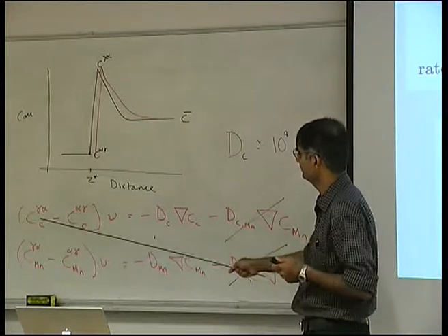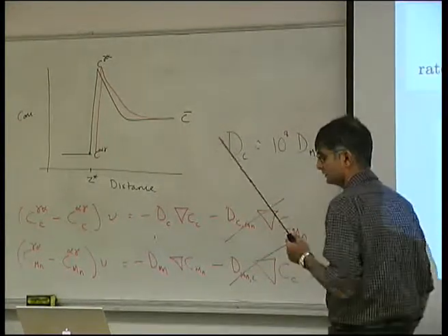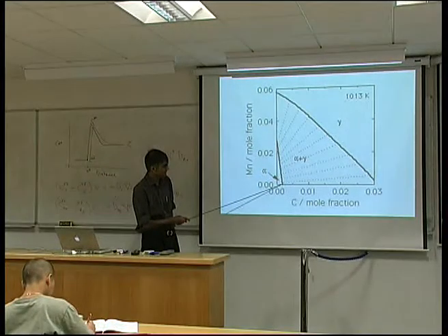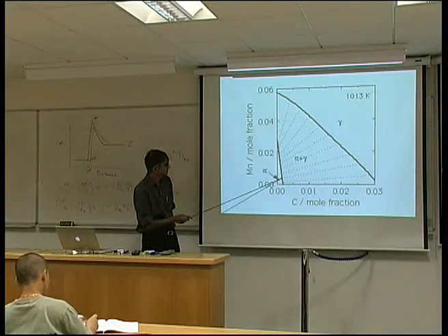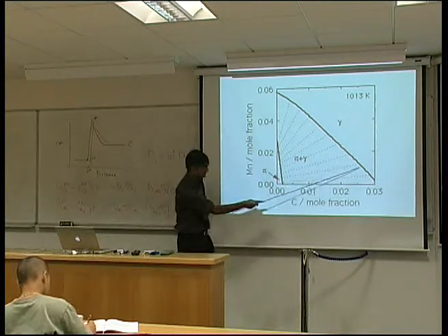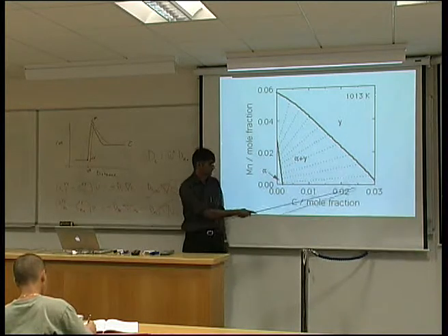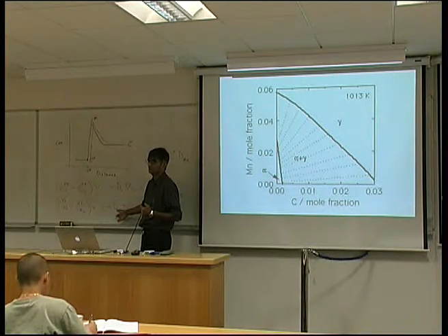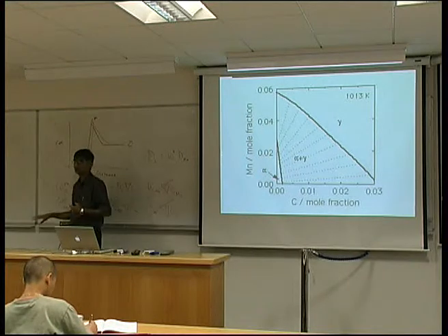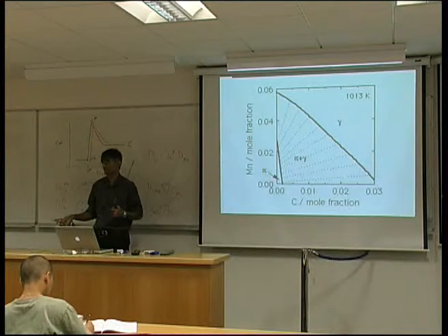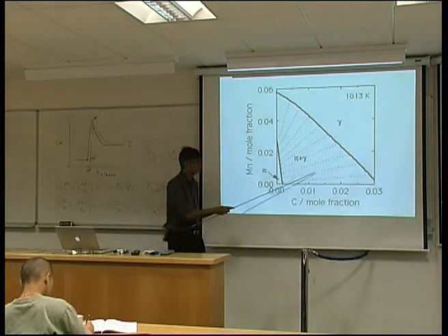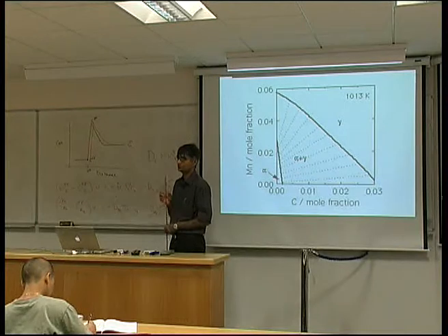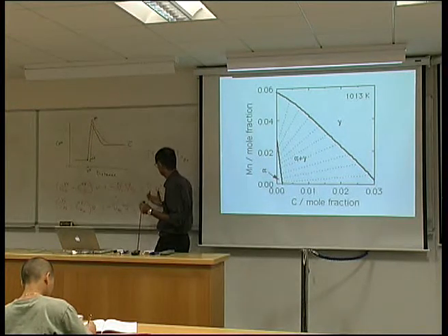You see, you could say these terms are different. If I take the values from the equilibrium phase diagram, then this is C alpha gamma carbon, and this is C gamma alpha carbon. They are different, and you might imagine that we could solve these equations, even though these are 8 orders of magnitude different. But the differences between concentrations are not large enough to account for 8 orders. So if I simply say that, look, if I have an alloy of this composition, it's this tie line, in general, we won't be able to satisfy these equations. So how do we solve this?